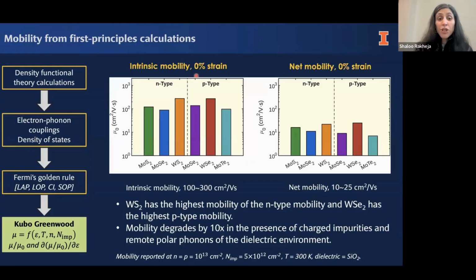We can see first we establish our intrinsic mobility of the materials at 0% strain. We can see that for most of the materials that we've looked at, which are listed over here, we've looked at both molybdenum-based materials and tungsten-based materials. What we find is that intrinsically, the material can have mobilities in the range of 100 to 300 centimeters square per volt second. But when we include all of those interactions with your oxide layers and the charge impurities, the mobility drops by a factor of 10.